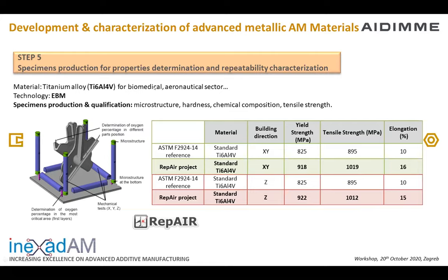processing by EBM. For example, here in this build production, we have here our critical part, and we need to control the oxygen content. We have here some small testers, but also we need to control the mechanical behavior for this specific application. So we put also a mechanical tester in both directions, in XY and also in Z direction. We also check microstructure. So this is our build production for qualification.